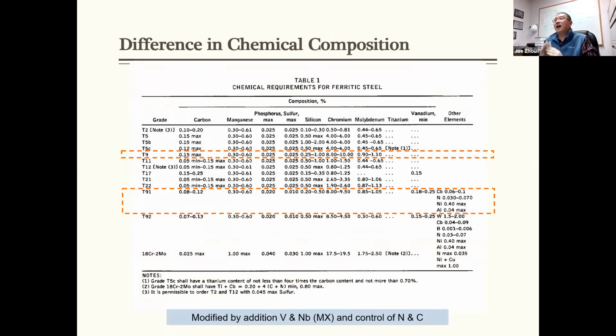Now, let's talk about what's the difference between grade 91 and a traditional chromoly steel. This is a typical composition table showing T2, T5, T9, T11, T12, T22, T91. You can see not only chrome difference and moly difference, grade 91 also tightly controls the vanadium. It also controls the niobium, controls the nitrogen, limits nickel, and also controls the aluminum. So that's a slightly complicated conversation.